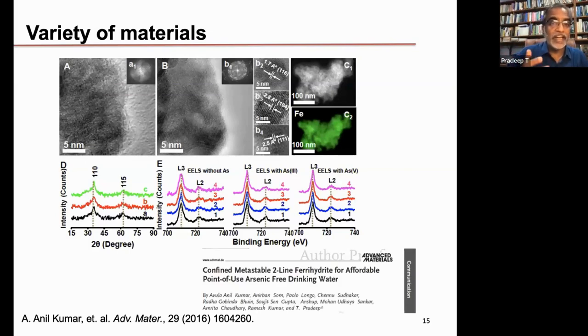But then you can have a variety of other materials. So imagine this to be iron oxyhydroxide. Well, the material that you create, the porous structures that you have, iron oxyhydroxide, it is not highly crystalline, poorly crystalline. So you do get some peaks in XRD, but in TEM, you don't see anything. But if you irradiate for some time, you see crystallization occurring, and you see smaller nanocrystals forming. And these are very tiny. So the grain sizes are very tiny. And you do what is called electron energy loss spectroscopy and a few other techniques to study this.